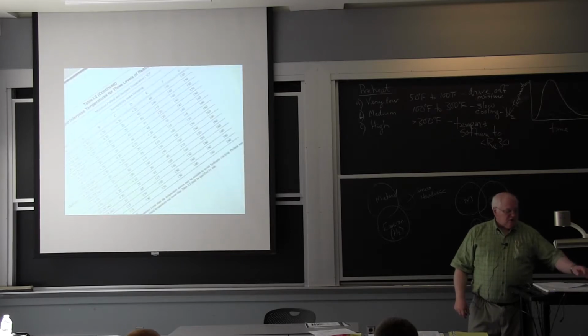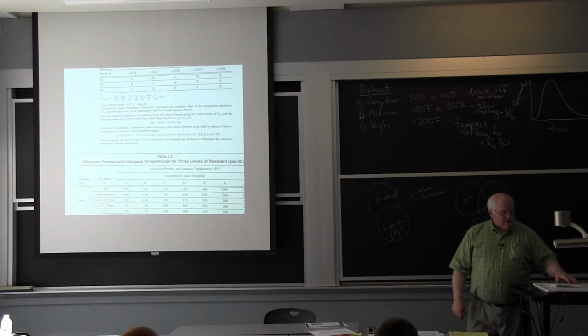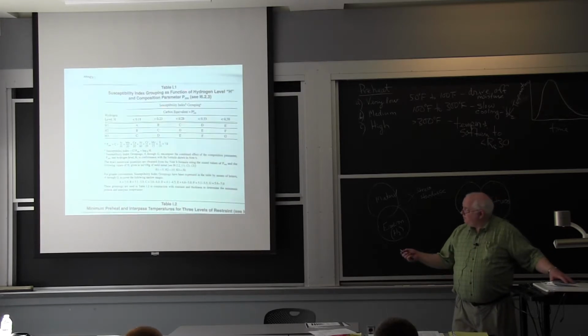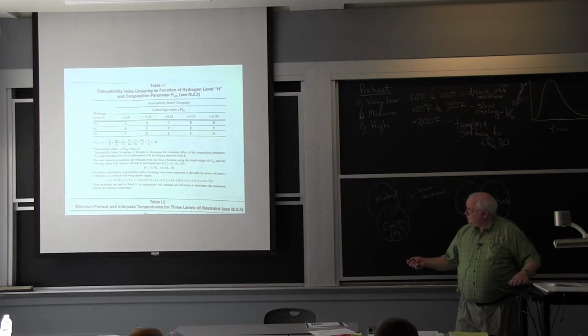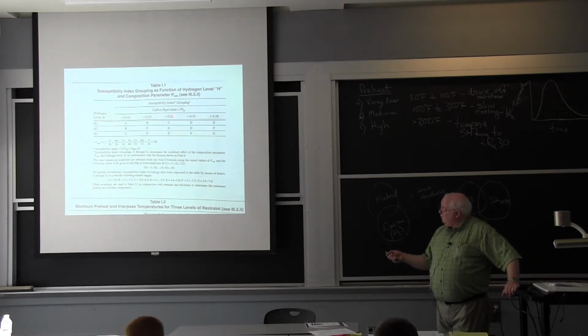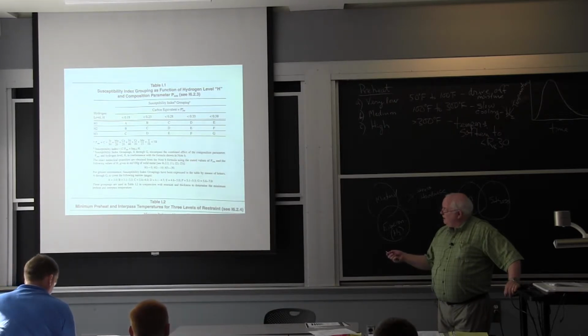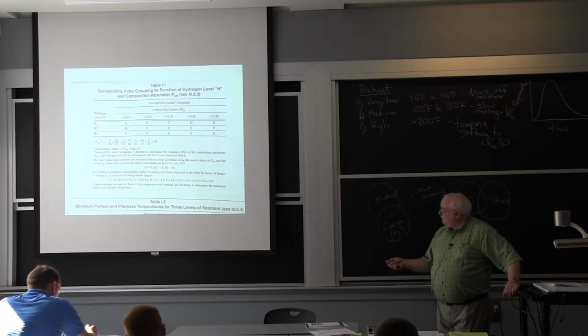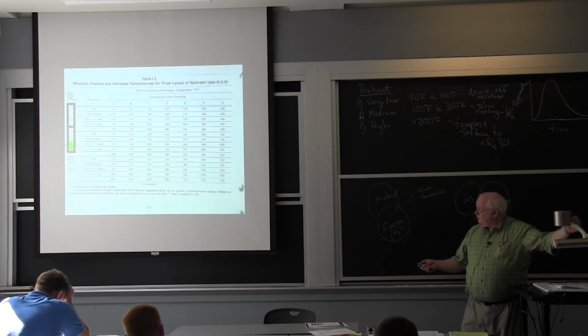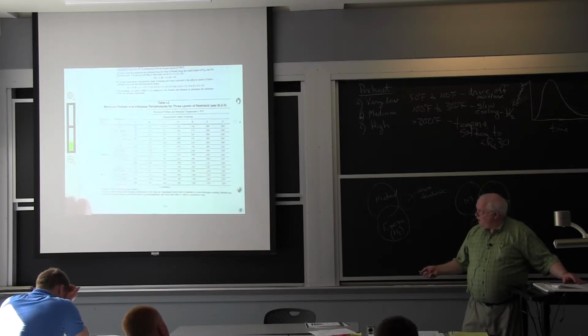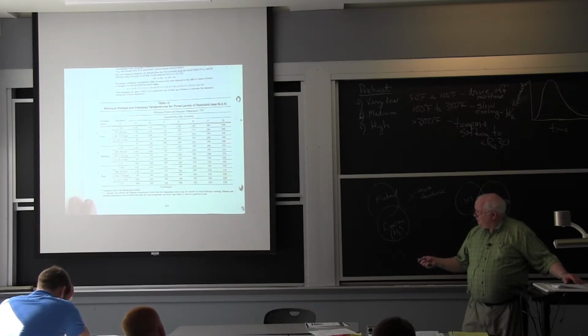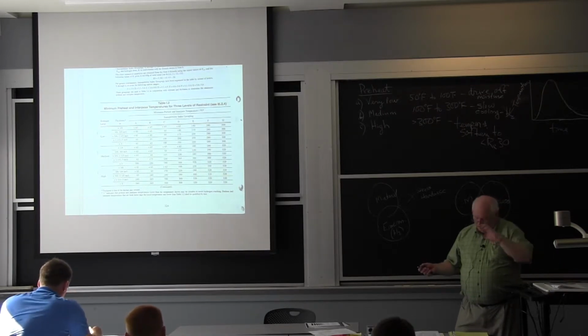And so now you come to the tables, and the first table you go to is susceptibility index for the groupings. So here's your hydrogen levels 1, 2, and 3. You have to look at your carbon equivalent and determine whether you're an A through G region, depending on the hydrogen and the carbon equivalent. And then you go down to table 2, and you can read off your preheat. Okay? It will tell you how much preheat to use, low, medium, or high restraint, A through G. The highest they have on here is 320 degrees Fahrenheit. The lowest is less than 65, okay, which means no preheat, essentially.